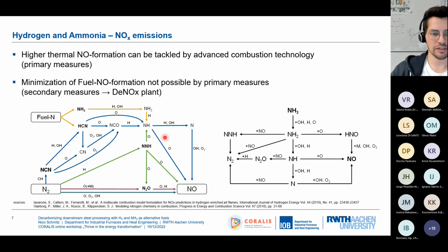The second point is about ammonia. Ammonia is one species which leads to fuel NO formation. So you see it's quite a bit more complicated here. We have several steps that can happen. The most important takeaway is that if we want to combust ammonia to nitrogen and water, we need nitrous oxide for that. So we need NOx to oxidize this ammonia. So it may not be possible to have low NOx combustion by only doing primary measures. And this could mean that we have to implement secondary measures in our furnaces, so DeNOx plants. This is not typical for us.